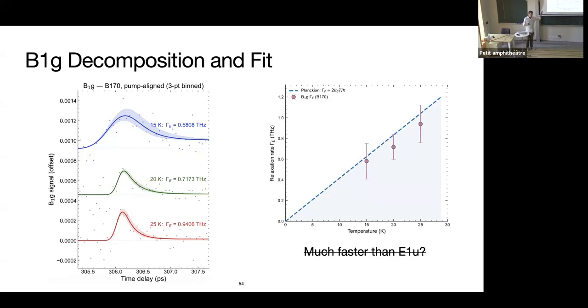So it is a relaxation rate which is different from that of the E1U, which is the transport relaxation rate, and has a kind of understanding in old school Fermi liquid theory, and that there's a kind of numerology about all these different possible excitations of the Fermi surface and the coefficient of their T-squared scattering. So this coefficient here is about 2, and it's the same coefficient that we find for the E1U rate in the case for the linear optical conductivity.